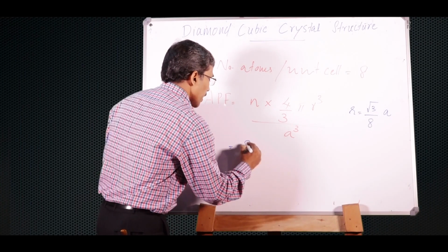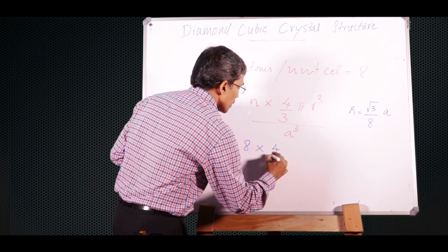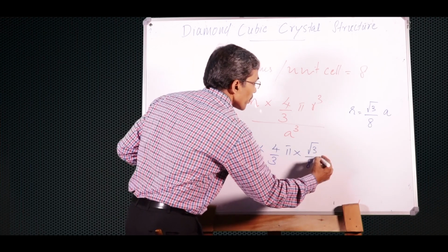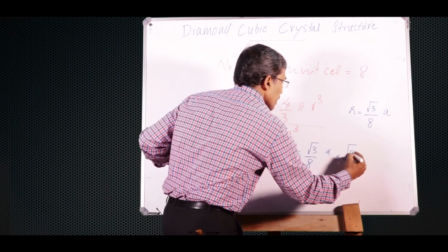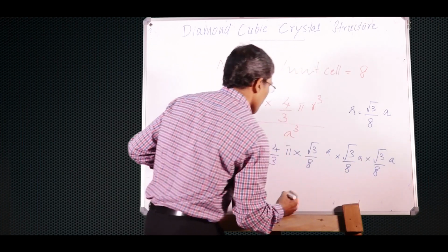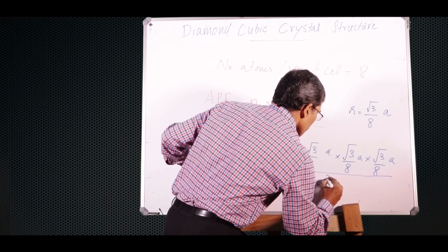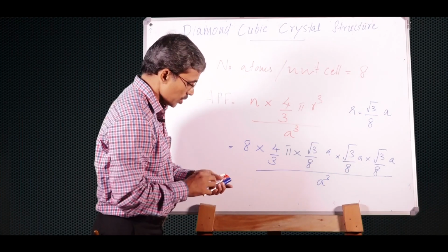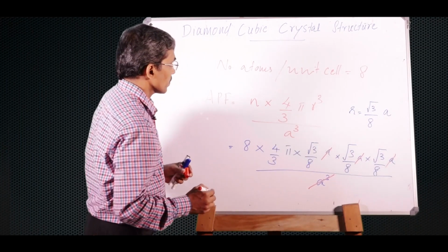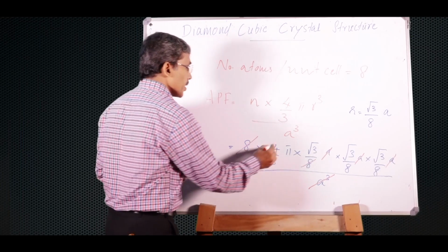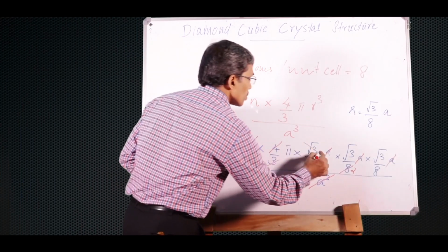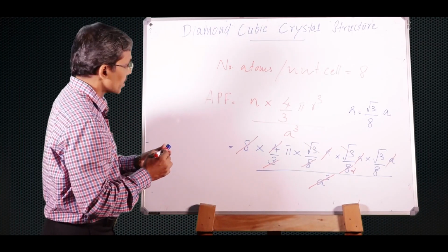N is 8 into 4/3 pi into √3/8 A into √3/8 A into √3/8 A divided by A cube. So this A cube and A cube cancel, 8, 8 cancel, this 4 and 8, 2, then this 3 and these 2, 3 cancel. So when you work out, you will be getting